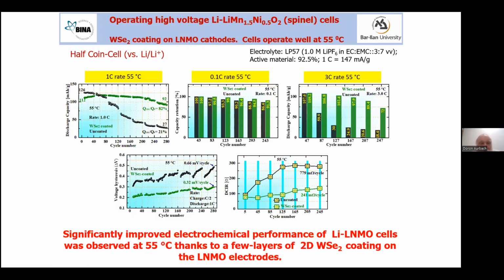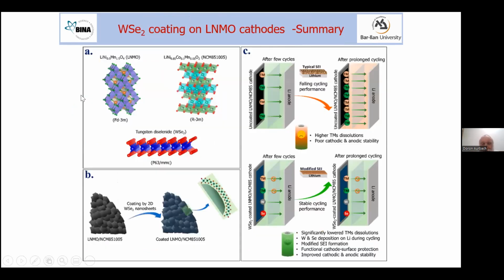We found that by using tungsten selenide, we now have a portfolio of materials. We have a physics option of layered materials like tungsten selenide on the surface, and we can demonstrate cycling even at 55 degrees C, and we can see very nice stabilization of the material. We stabilize the capacity, we stabilize the voltage, and it appears that by coating the cathode with tungsten selenide, it also affects the lithium or graphite negative electrode as well.